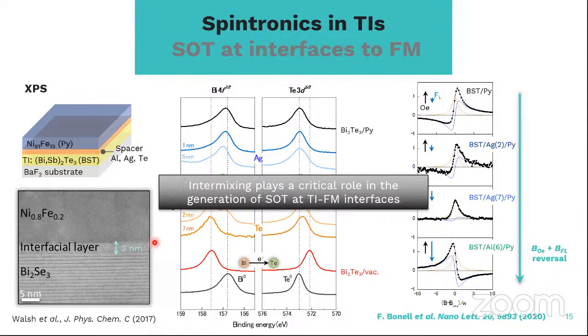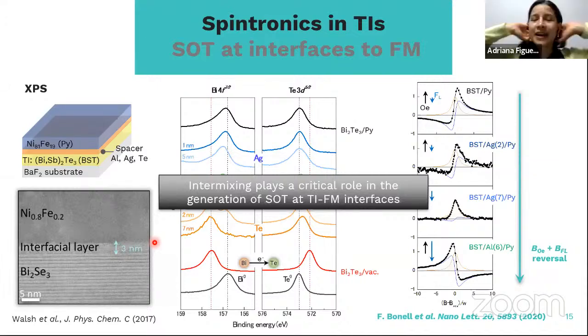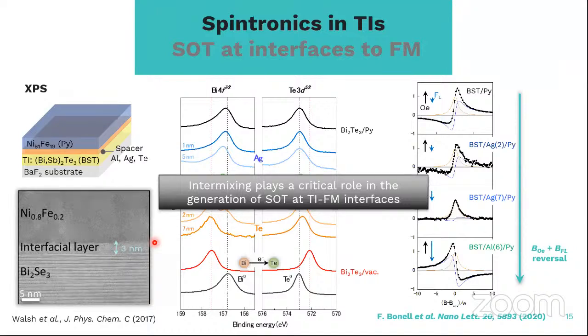Because we will have different spin diffusion lengths because there are different materials and values. Yeah, but unfortunately we didn't have clear TEM images, to say, okay, at this part and in this kind of system or with this interface we have this thickness, and so on. Unfortunately not, so we made an estimate. And you have to know the resistivity for each layer too, so it's more tricky. It's not easy, but yeah, we did some estimation.